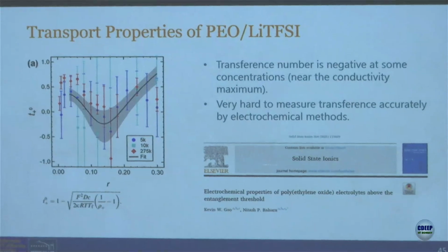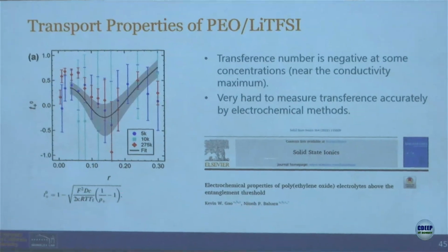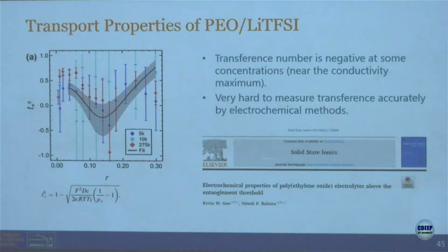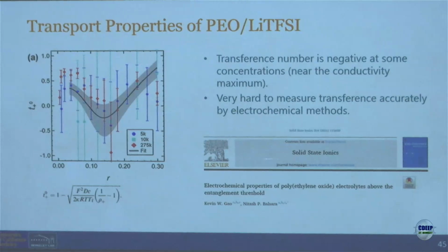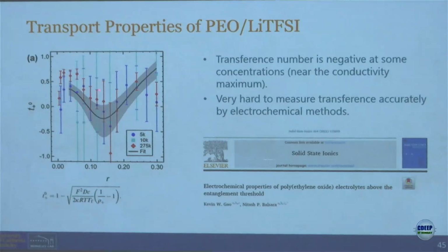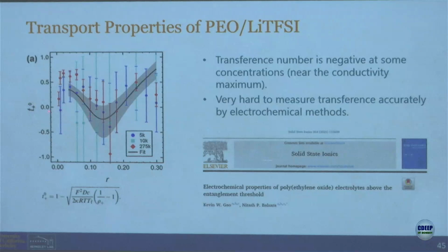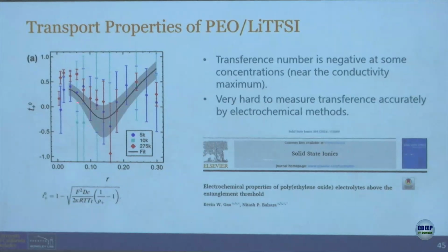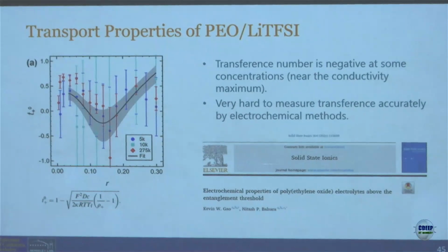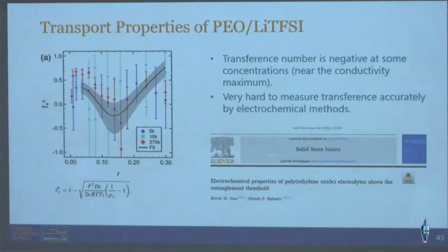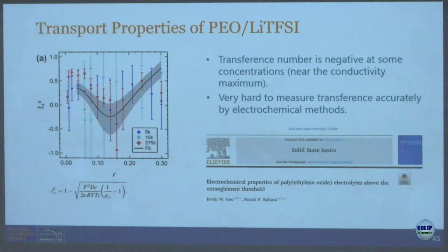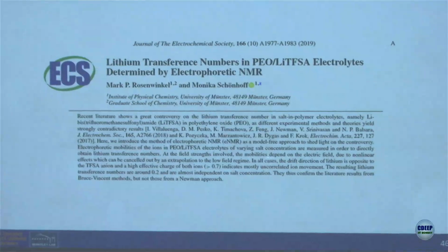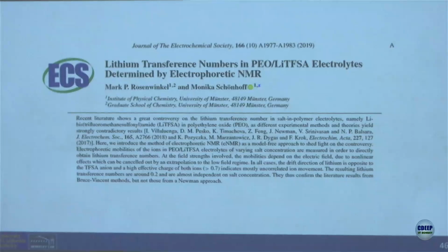This is a plot that we proudly publish because we think it's the best measurement of transference in the literature. And when you do a best analysis of all of the data, what you get is the horrible realization that this number is negative in a broad range of concentrations, to our best estimate. This is problematic.